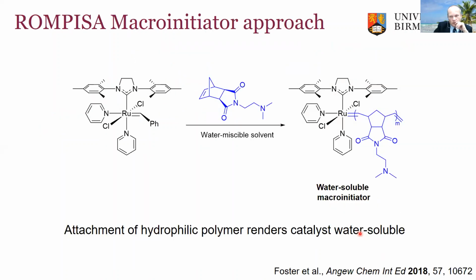So what we looked at was what we were terming our macroinitiator approach. So just a very simple concept where we take a commercially available Grubbs type catalyst. We just add on a few water miscible monomer units onto the catalyst, and this then makes it soluble. So rather than the conventional approach of modifying the ligands to have charged groups to solubilize the catalyst, we just took an insoluble catalyst and added a few monomer units to make this water-soluble macroinitiator, which renders the catalyst water-soluble, and then we can use that water-soluble catalyst and polymerize any monomer that we want to form the basis of our hydrophilic macro-CTA and the first block